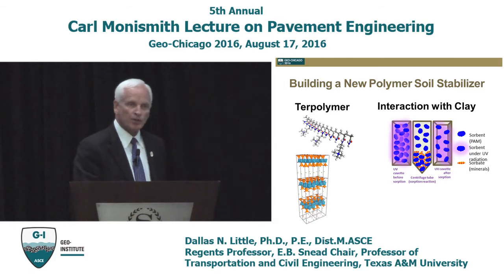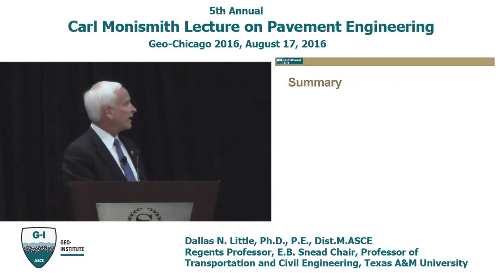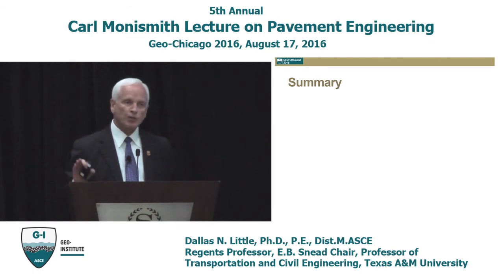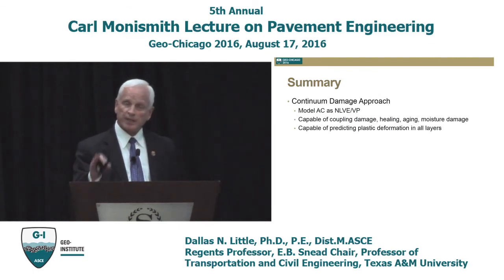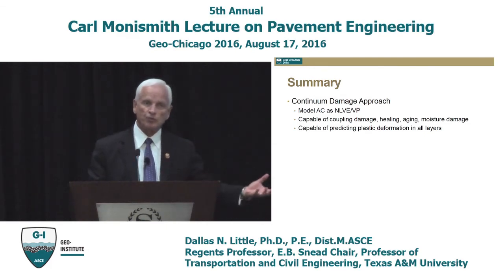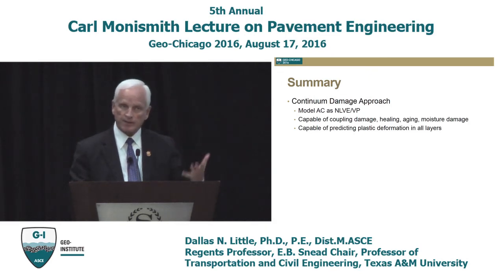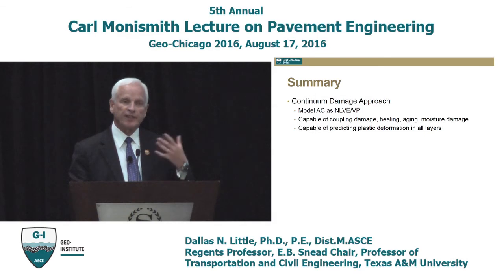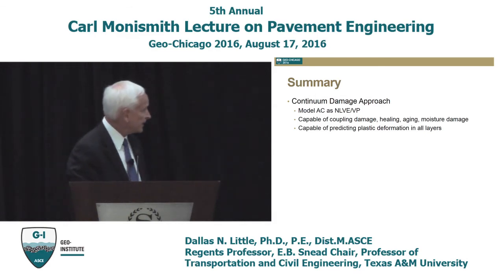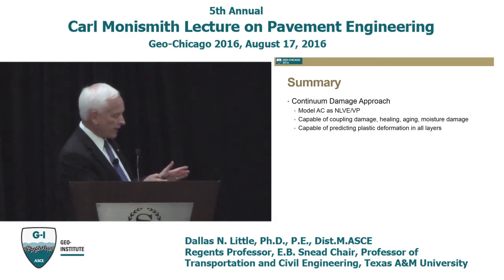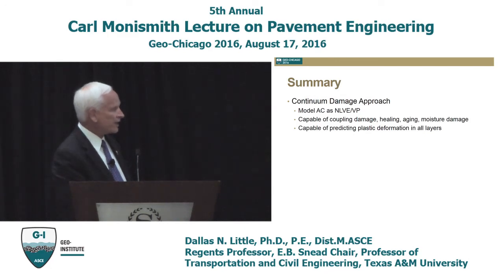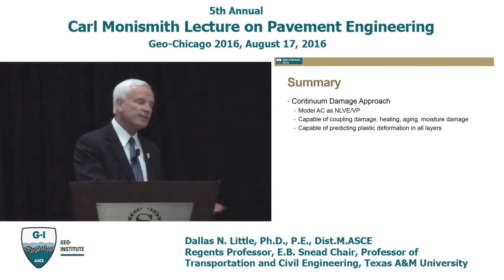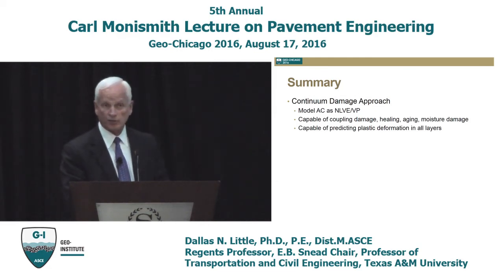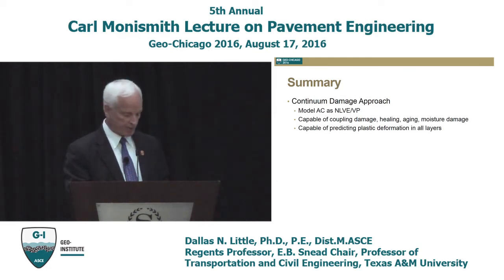Okay, for the sake of time, I'm going to really quick kick to the summary. We have talked about a continuum damage model that has weaknesses, but it has the great strength of being able to couple different processes, like mechanical damage with moisture intrusion, weakening because of moisture, the effects of aging, and so forth. It is a nonlinear viscoelastic, viscoplastic model, capable of evaluating fatigue and healing, and capable of predicting plastic deformation, both in the asphalt layer and now in the granular layers.